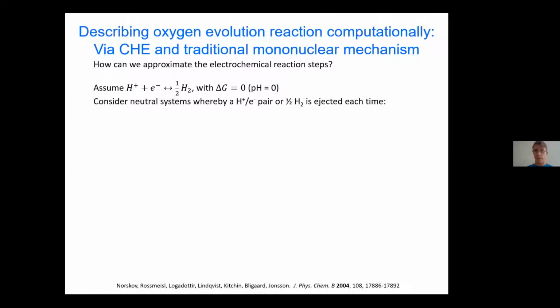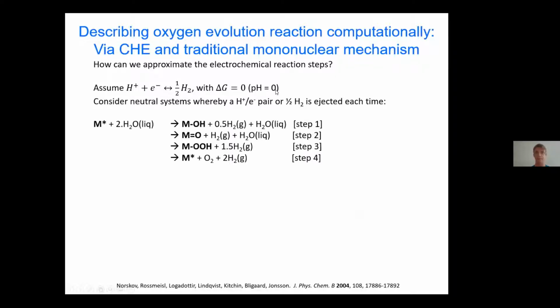So now to the computational hydrogen electrode. We can approximate these electrochemical steps by assuming that one proton-electron pair is equivalent to half of a hydrogen molecule. So this reaction has a free energy of zero at pH zero. And then we can describe four different states of the system.